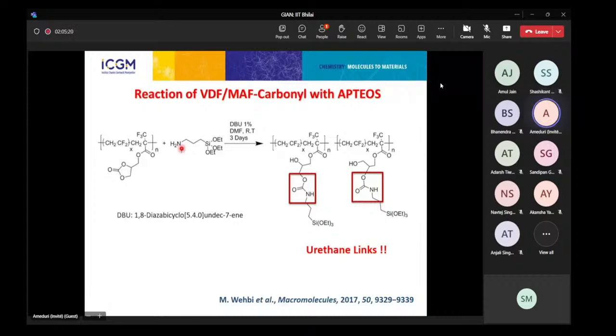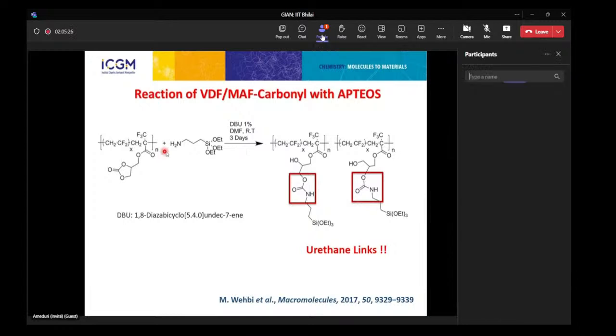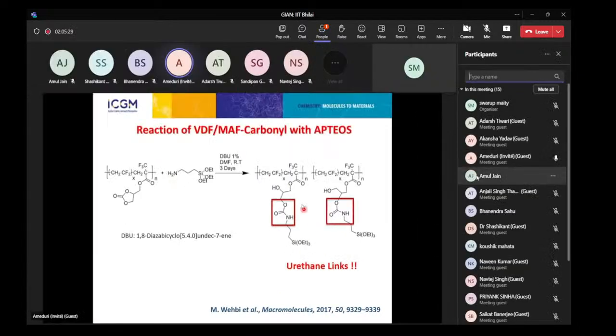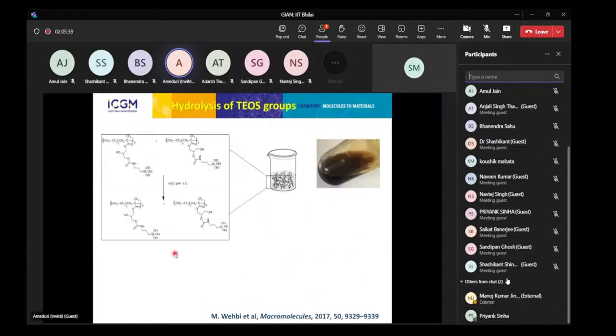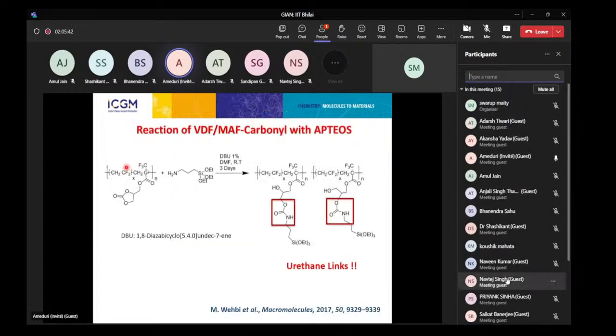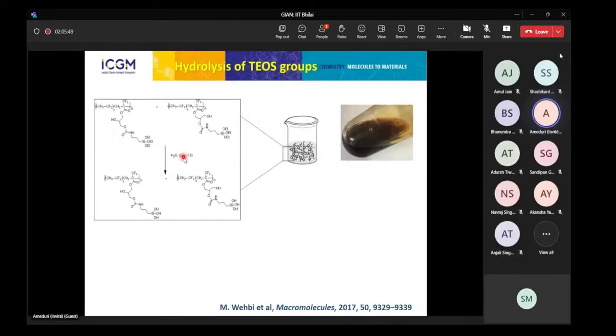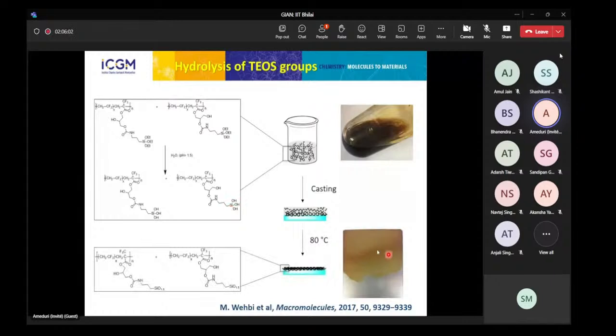The nucleophilic reaction of amine onto the cyclocarbonate, this is now the new generation of polyurethane, makes this urethane link with a secondary alcohol or primary alcohol, which enables to have a very stable urethane link. And it was possible, by adding this trialkoxysilane, to make some hydrolysis and condensation. First hydrolysis under low pH, because one of the drawbacks of PVDF is the sensitivity to base, and then to allow the condensation by heating, casting, and making a film also onto some steel plaques.